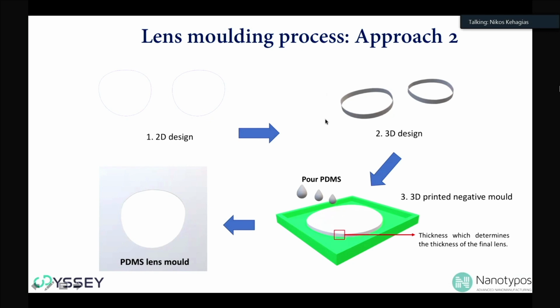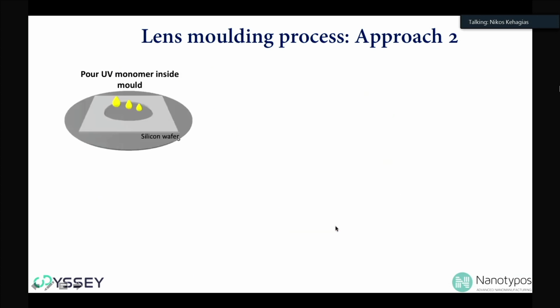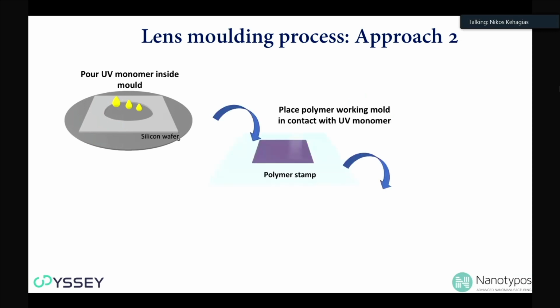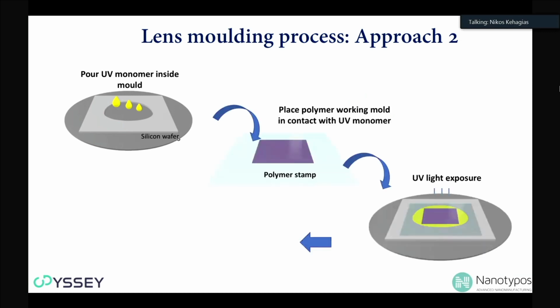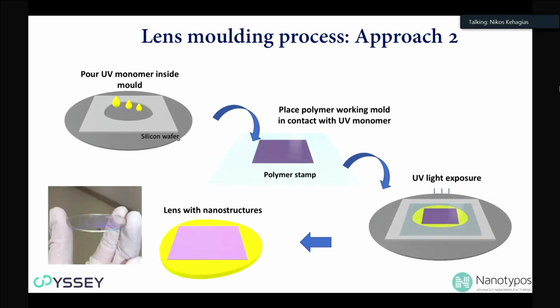So we took the actual 2D designs of the lens that the end client would like. We 3D printed a hard mold, which we replicated in PDMS, and attached that PDMS mold to a silicon wafer. So we created our own universal mold. We pour in our UV monomer. This is the monomer that we developed. And then by placing the polymer stamp on top and exposing to UV light, we can really structure the complete targeted lens product.